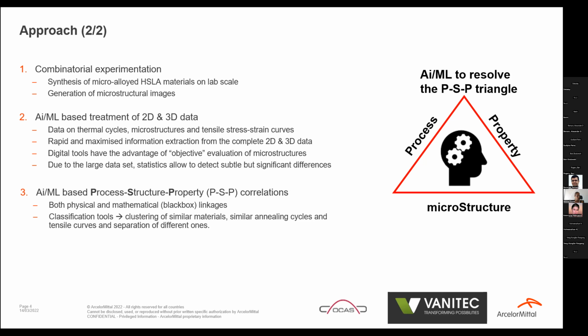Not only microstructural images, but mechanical properties through tensile testing will also be gathered, and the precipitation states through ICP-MS, so the fraction of precipitates will also be studied. This collection of 2D and 3D data will then be analyzed by means of the artificial intelligence tools mentioned, so we have a more objective evaluation of the data collected on these materials with varying compositions and processing steps.